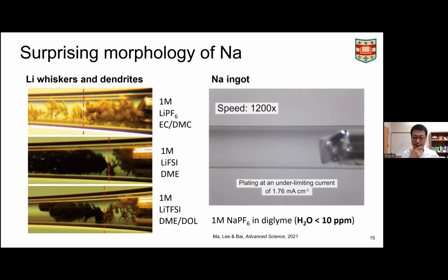So you can see that it grows like a big chunk, right? It grows like a rod. It's 100% solid. You don't see any pores. You only see this shiny facet, right? Extending into the electrolyte. And this structure has a scientific term, ingot, but it really just means totally different from the whiskers, from the dendrites we see in the lithium system, okay?